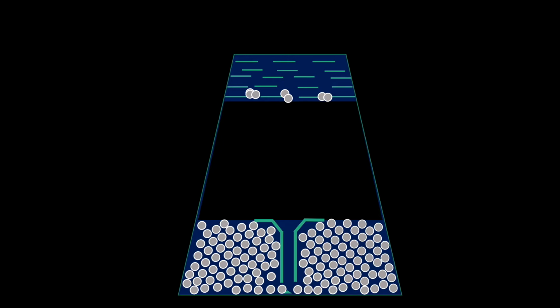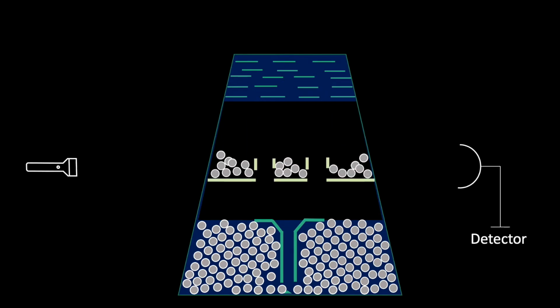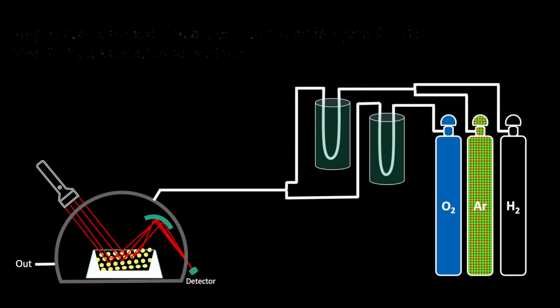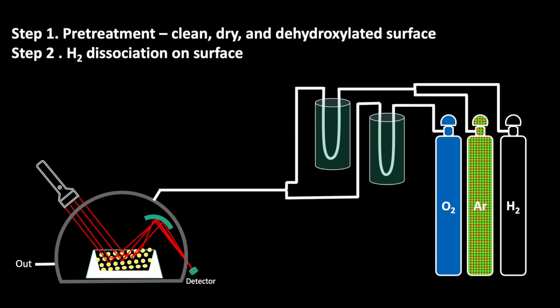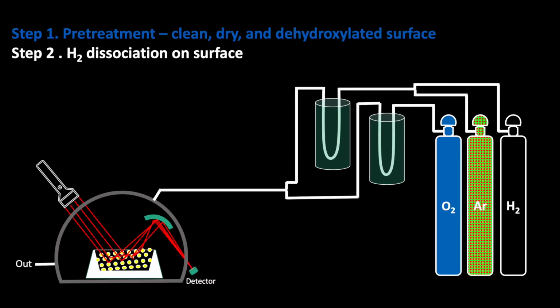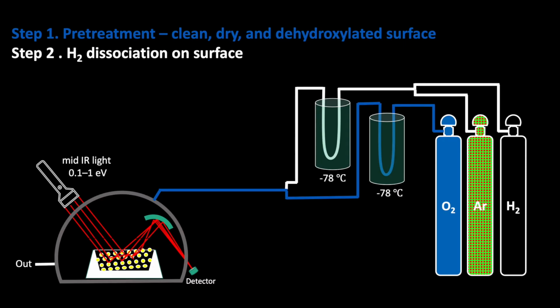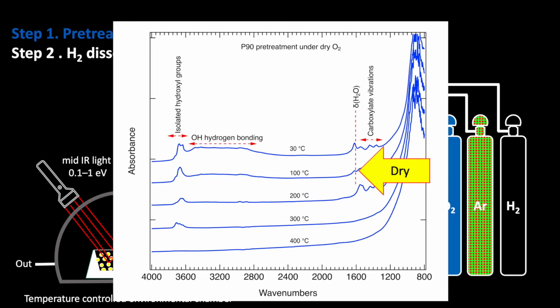Now, if we have any empty or unoccupied states in the band gap, these electrons will populate them and we can determine their energies spectroscopically. A typical experiment includes two main steps, pretreatment and hydrogen dissociation. In the pretreatment step, we increase the surface temperature stepwise under a very dry oxygen gas flow to prepare a dry and dehydroxylated surface without any carbon contaminants. During this step, we monitor the surface using diffuse reflectance IR spectroscopy.